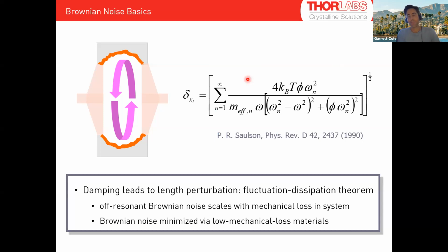And what you have to keep in mind, I showed that expression earlier, which is the noise expression. It is the infinite series of all the mechanical resonances of that body. So there may be mechanical modes that strongly perturb the length of the cavity, and those will have a big impact, but there may be some mechanical modes that don't do anything to the cavity. They're still in there and they have a small contribution, but it'll be minimal. But you have to sum up all that infinite series of modes there, look at the off resonant contribution from each, and you have to minimize that for all of them.